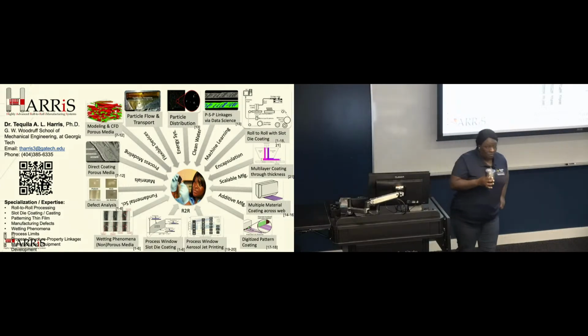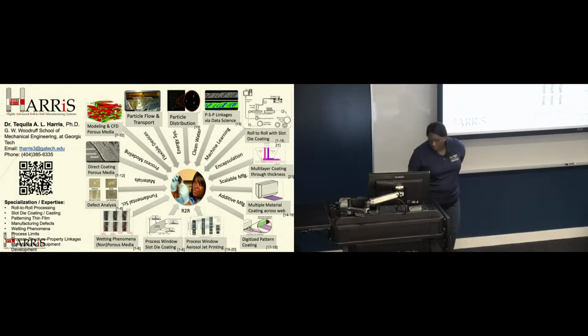Thank you. In the multiple material coating, can you please tell us what's the minimum length you can achieve? Minimum, and if they have overlap or not. Thank you. So, minimum width or length? Width. So the minimum width that we've gotten to is, again, somewhere between 40 and 25 microns. But the limitation there is technically our ability to cut, because there are some cutting operations beforehand, and the vibration in our roll-to-roll. So we believe once those are mitigated, we can go even finer and smaller.